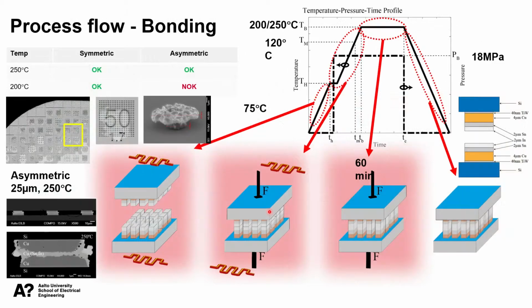Here the basic processing parameters are shown. During the bonding, wafers are aligned and preheated up to 75 degrees centigrade. At that temperature, the pressure is applied and then the wafer pair is heated up to the actual bonding temperature, which in our case were either 200 degrees centigrade or 250 degrees centigrade. The bonding time was 60 minutes, and after that the pressure was released and the wafer pair cooled down.